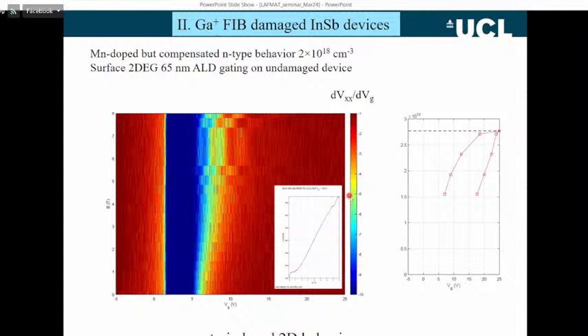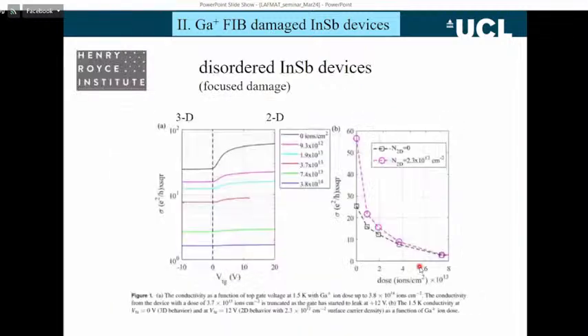So what we see in this material is we have a very, very highly conducting surface region and then a disordered bulk region. So we started to use these devices to look at disorder, but we knew that we would have this highly conducting surface region depending on the gate voltage. What we then did with this material was to disorder it, to introduce disorder deliberately.